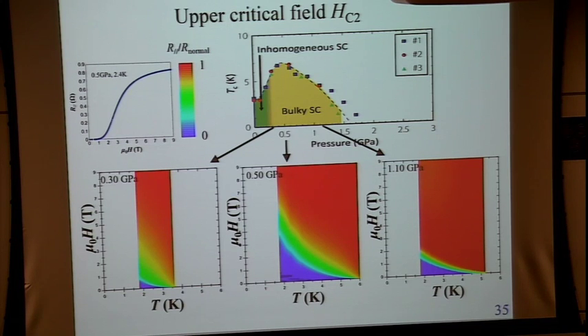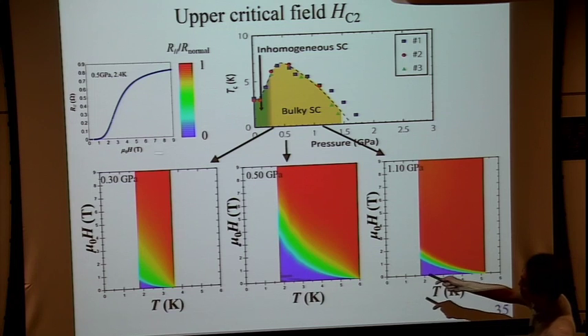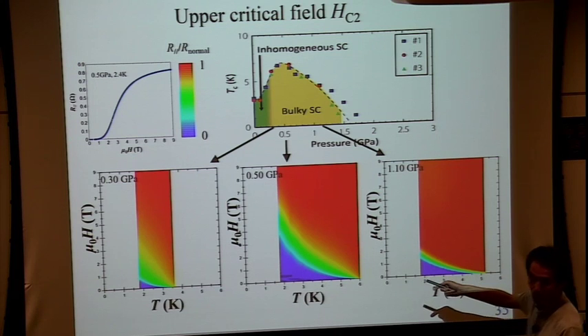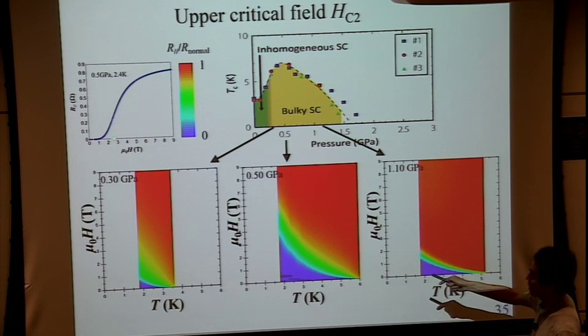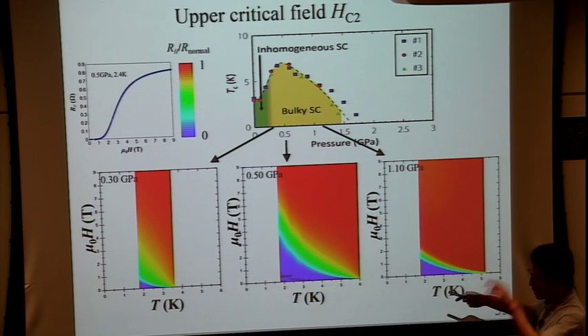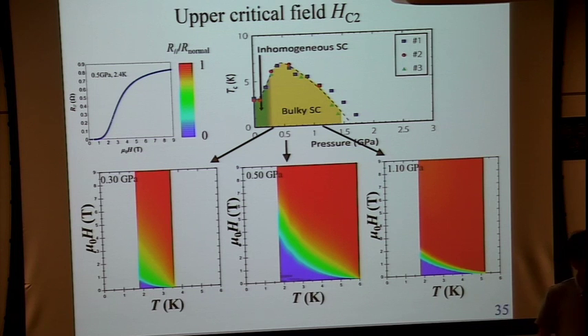Okay, these are resistivity measurements under pressure. And for example, you see the magnetic field and resistivities. At low magnetic field, it's superconducting and resistivity is vanishing. However, magnetic field kills the superconductivity and gradually changes the resistivity. The magnetic field is applied perpendicular to the layers, and this material is strongly two-dimensional. So in these situations, namely under the perpendicular magnetic field, vortex liquid-like states occur.